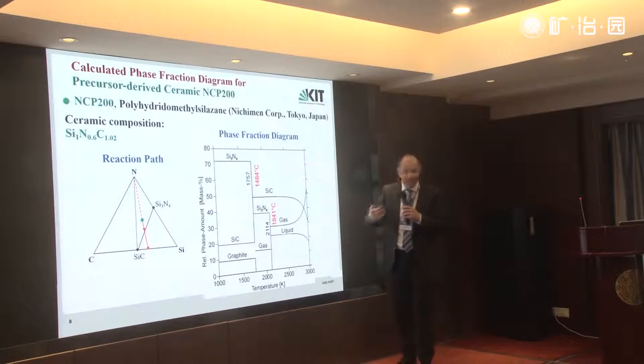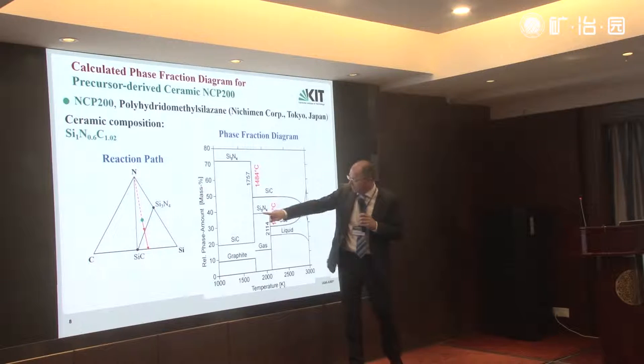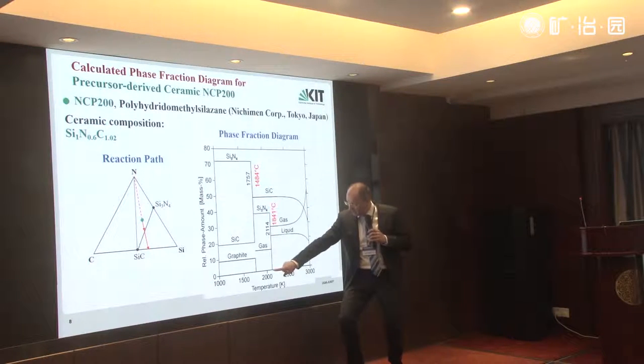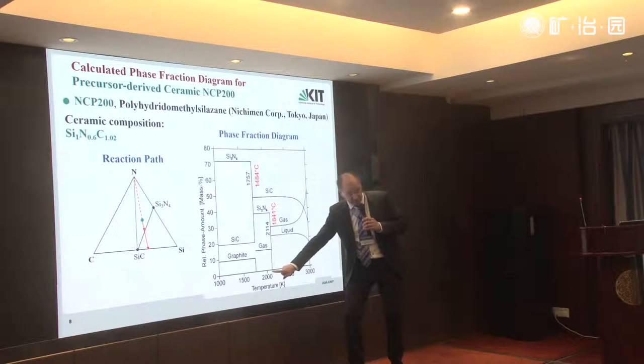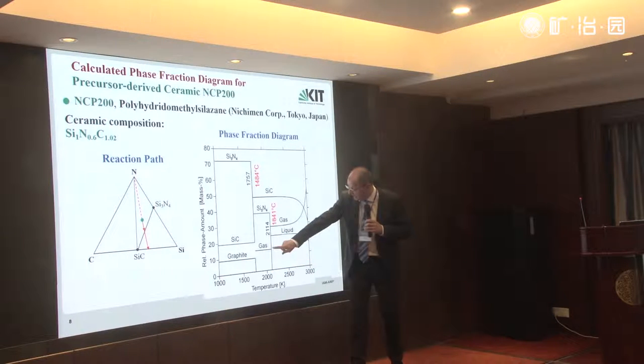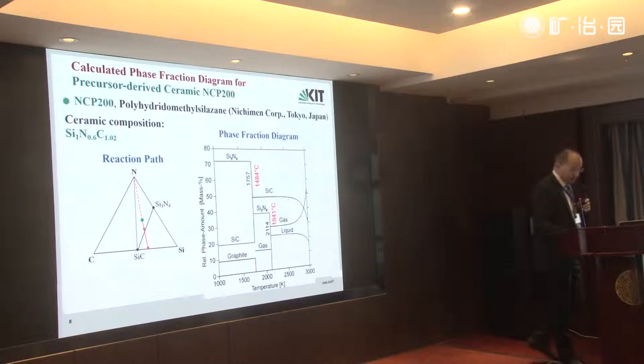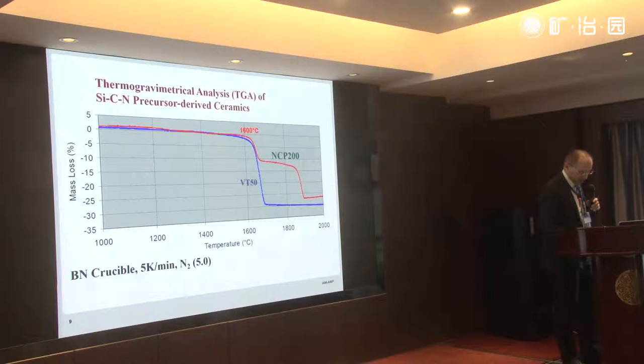And when we increase the temperature even further, we may have the decomposition of the silicon nitride. You see here, it goes down to a level of zero, it decomposes, and the gas phase, the nitrogen, is forming here, so an additional release of about 15% of nitrogen.